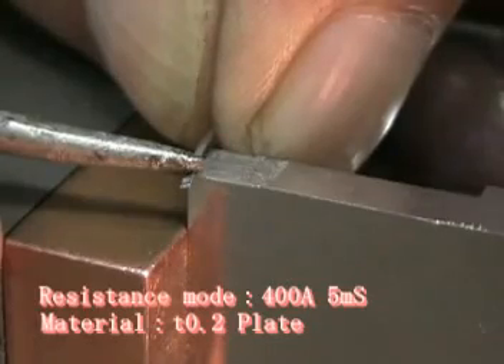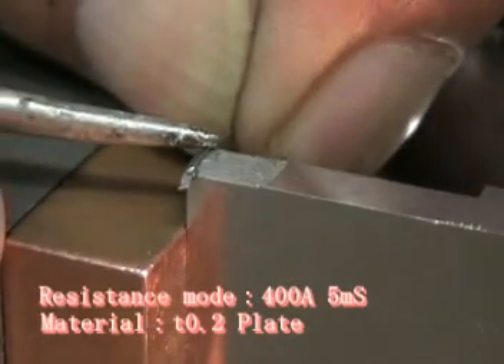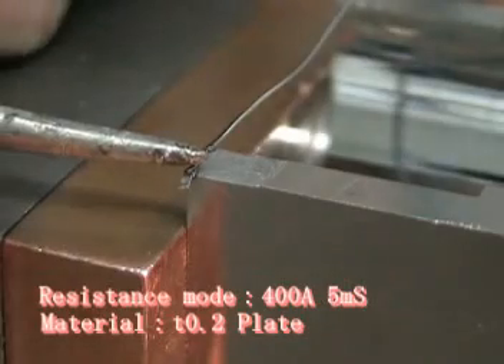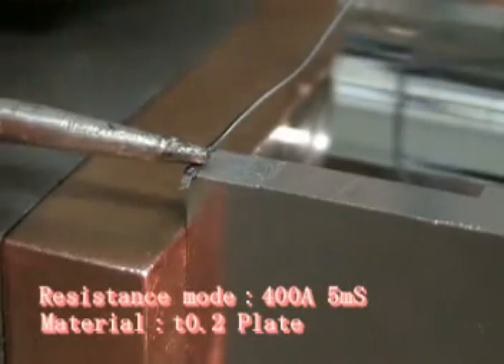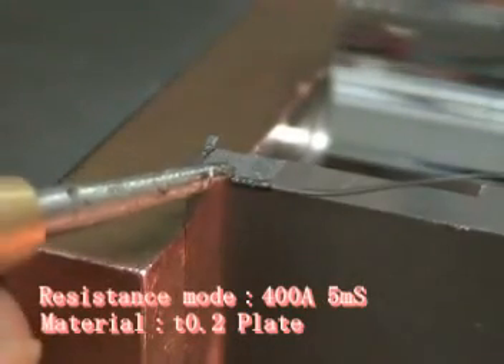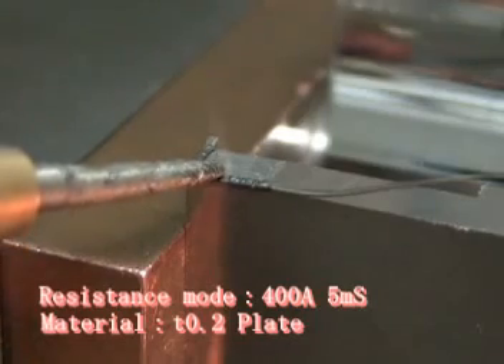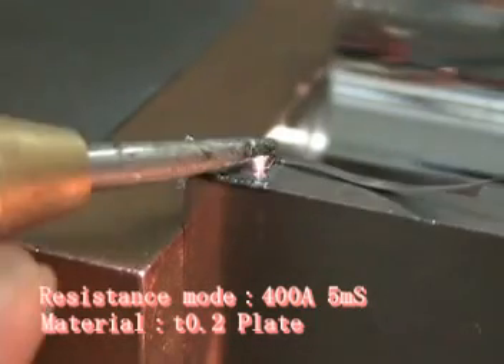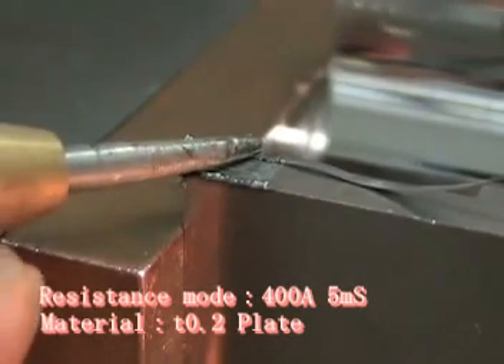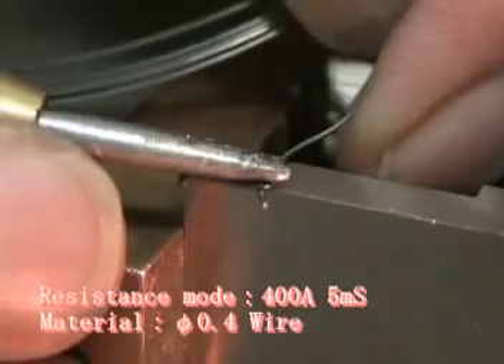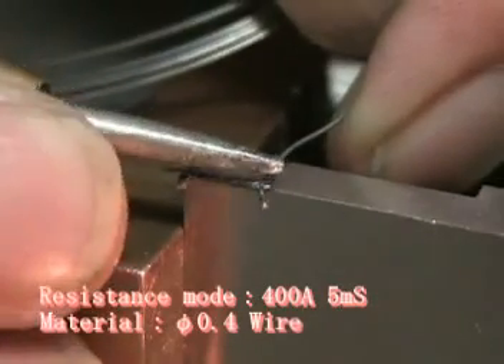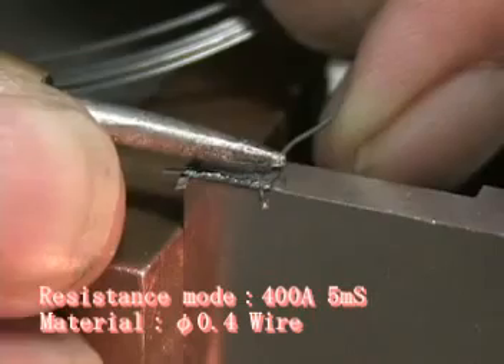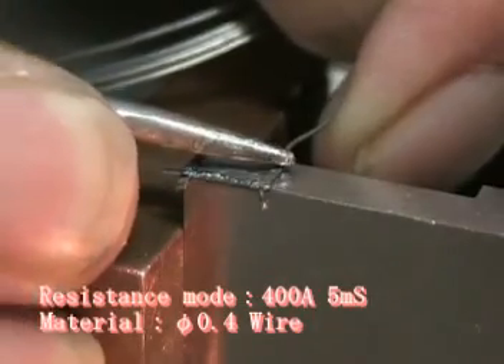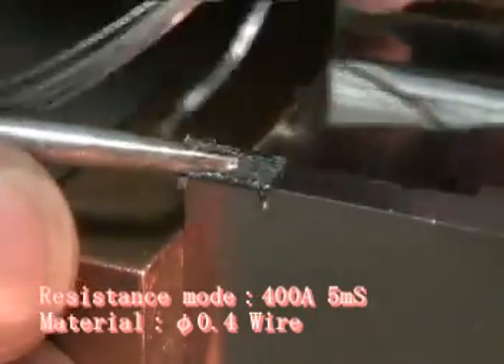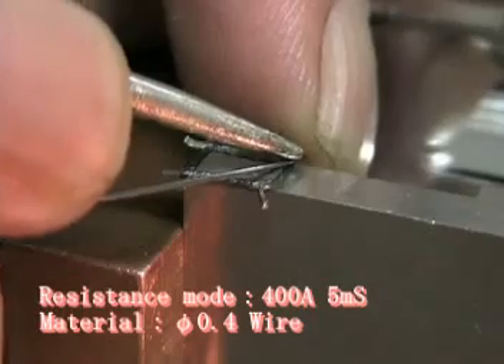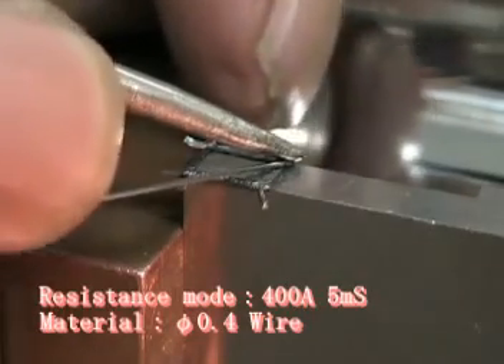Cut plate materials around 1 mm in width and fix 3 sides facing the outside as explained during the demonstration for fixing a parting line. Wire material is used for the remaining side. For this kind of repair, it is important to use enough welding material so that it sticks out of the edge as in the repair of 3 plain corners.